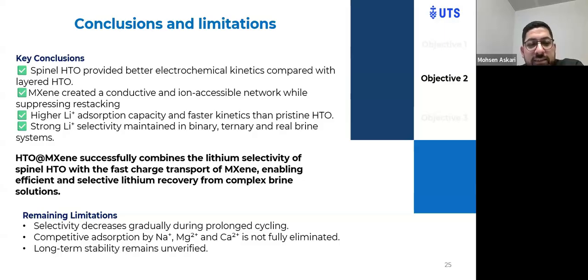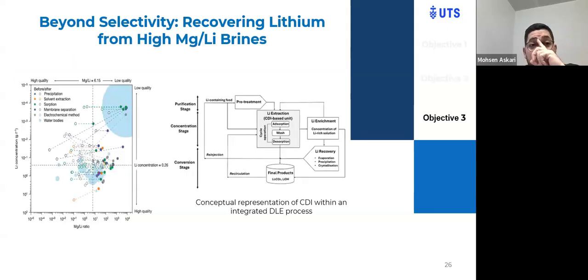The remaining limitations are that selectivity decreases gradually during prolonged cycling, which is one of the main challenges in CDI systems, and competitive adsorption by sodium, magnesium, and calcium is not fully eliminated. It affects the lithium selectivity in the next cycle, and the long-term stability remains unverified. Based on this idea, we went to objective 3 to look again at the position of the CDI in this DLE process. The CDI is the intermediate process that can extract the lithium and provide the lithium enrichment process.